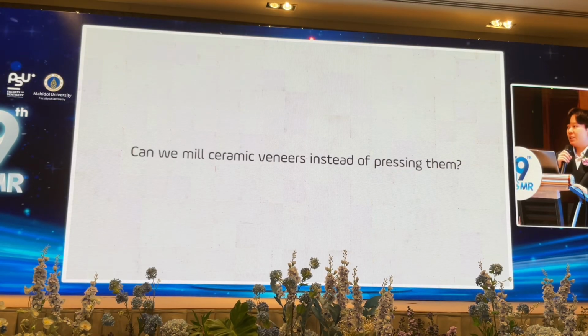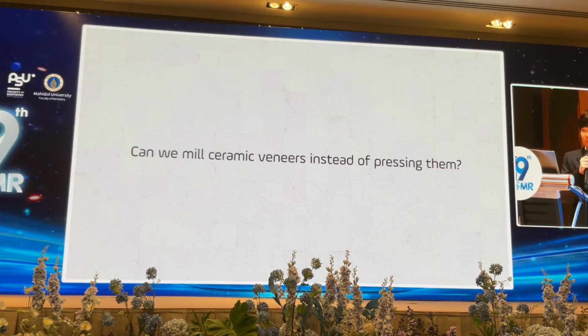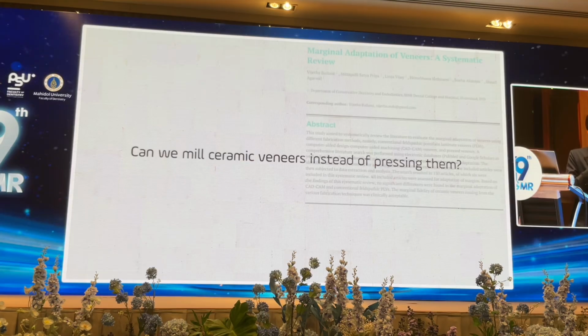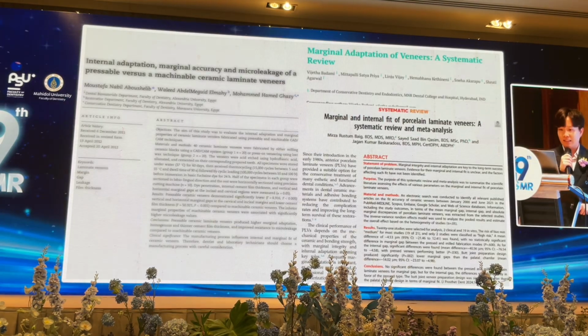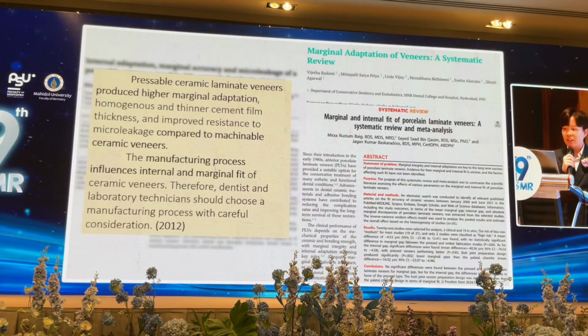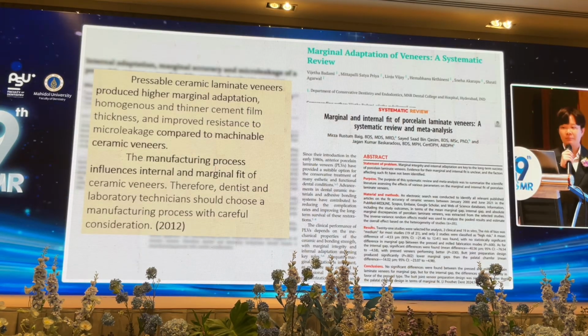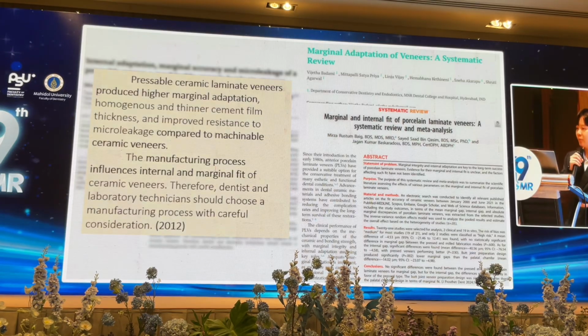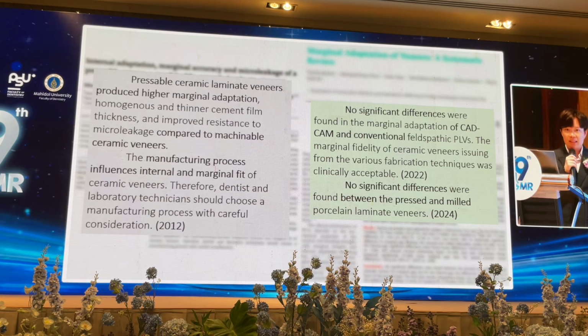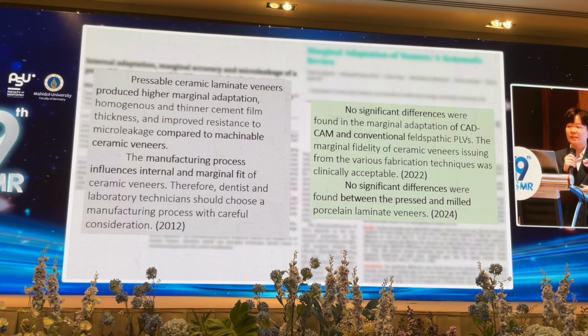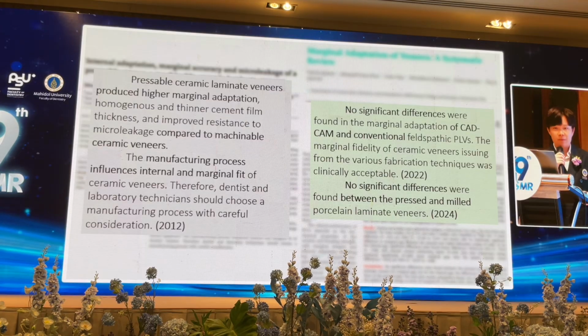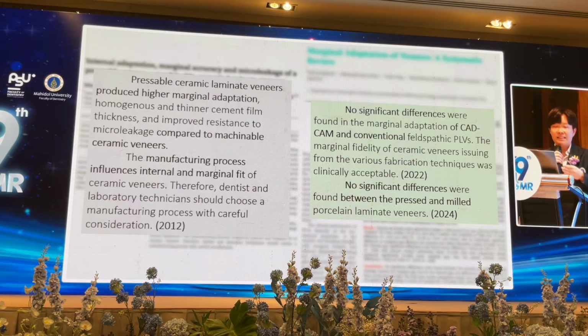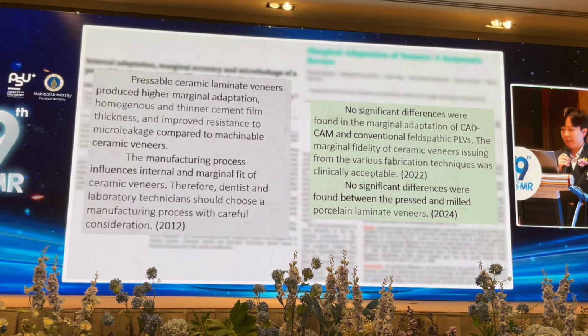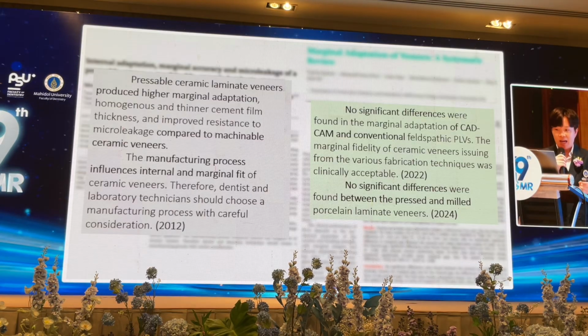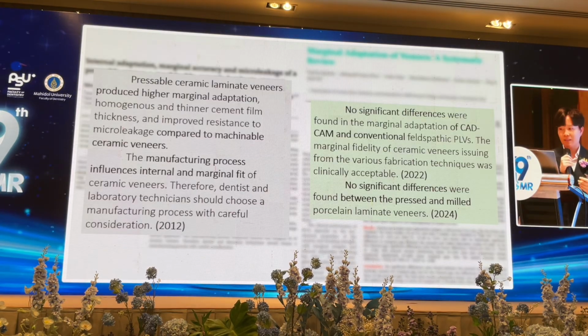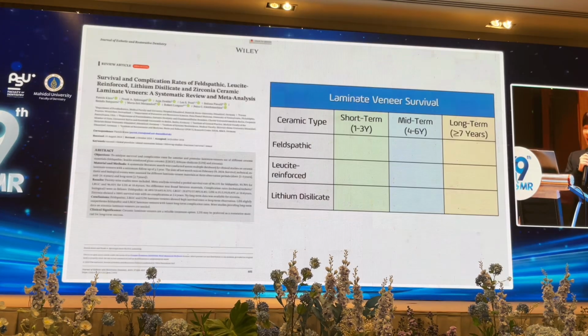But in terms of the digital way, you may have a question: can we mill ceramic veneers instead of pressing them? So there are a lot of studies. In the past, some studies showed that milled glass ceramic tends to have poorer adaptation and marginal fit when compared with the pressed one. But when we look at newer studies from 2022 to 2024, the story has changed. No significant differences were found between pressed ceramic and milled ceramic in terms of marginal fit and overall properties. So it shows how far our technology has developed. What used to be a limitation has now become a reliable option.